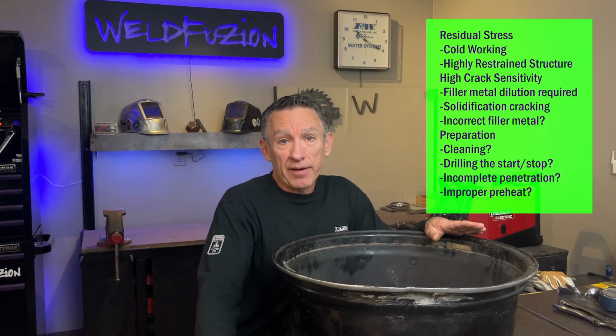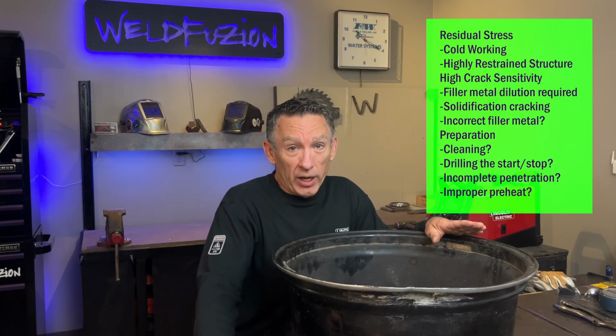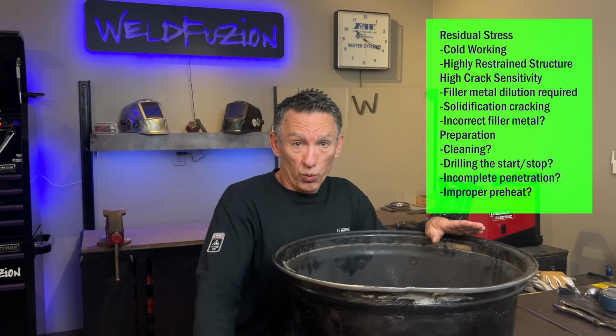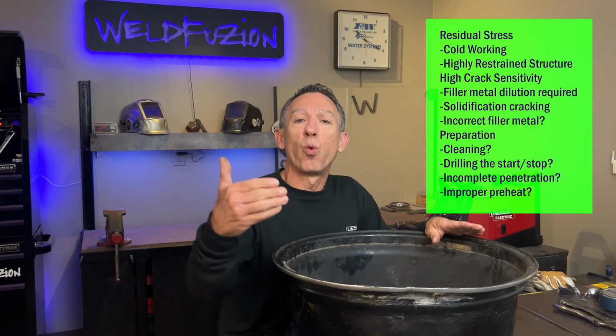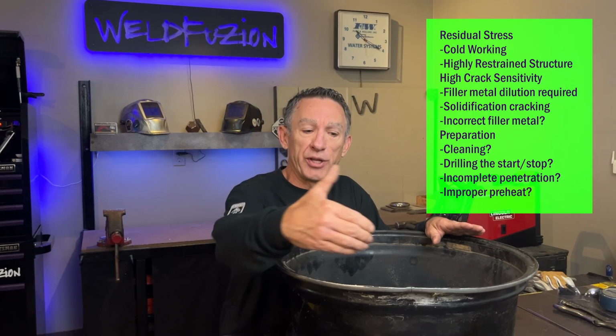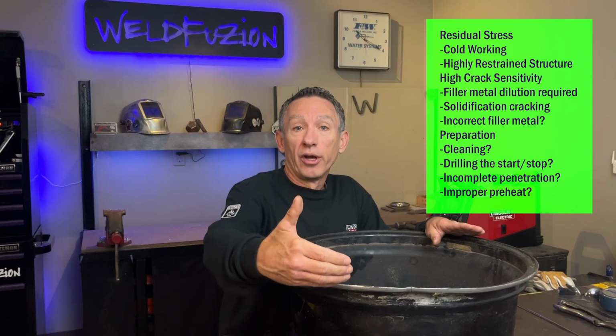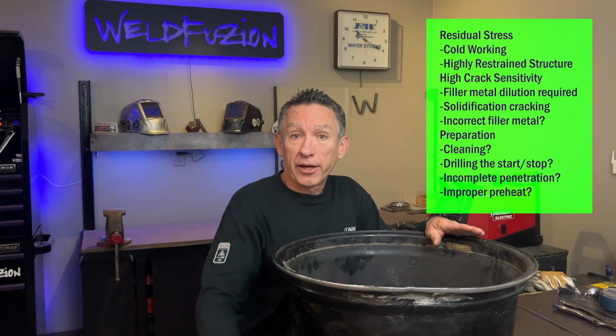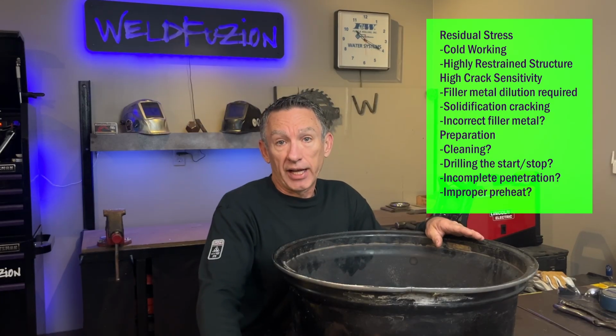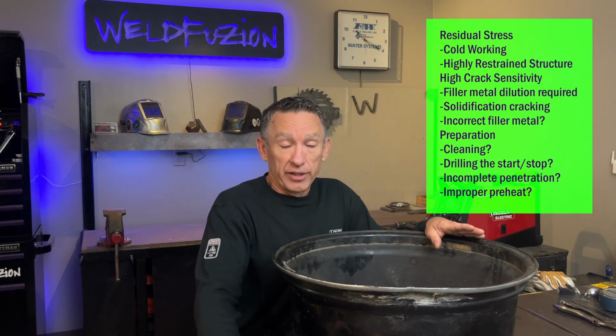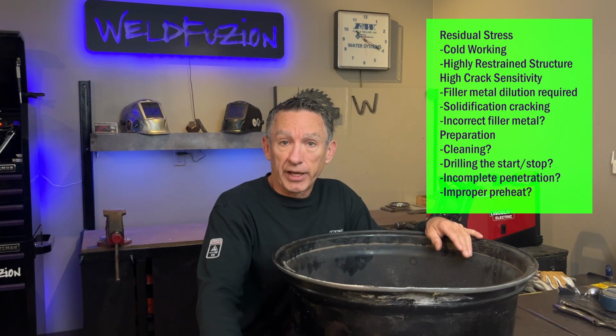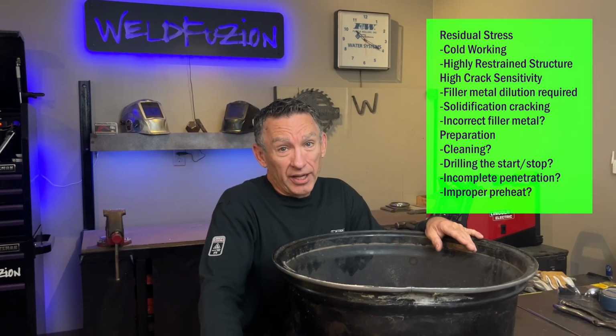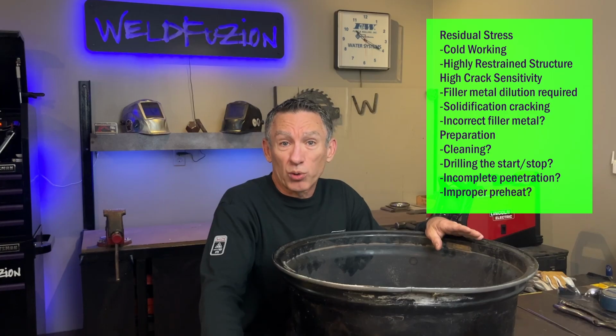The next thing that we have to consider is aluminum is highly crack sensitive. Very few alloys can actually be autogenously welded without filler metal because it requires the right amount of dilution between the base metal and the filler metal so that the weld doesn't crack immediately after it's put in. That's called hot cracking, solidification cracking, centerline cracking, and that's what we see as aluminum fails. So it's possible that they used maybe the wrong filler alloy, and that takes me into welding procedures and practices.